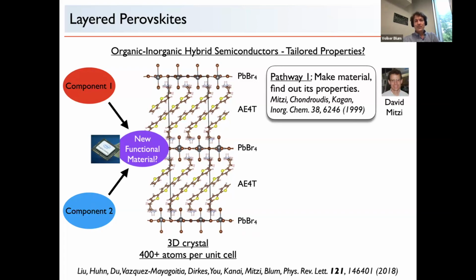This here is actually not an invention. So this is a three-dimensional crystal. It can be made. David made it. He did Laue diffraction, refined the coordinates. It's 400 atoms per unit cell if you don't have any disorder in the refinement. That's a serious endeavor, but we know that this material, as shown here, actually exists as a crystalline material.